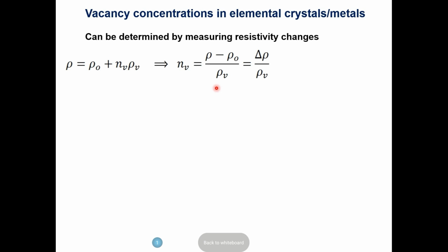Keep doing it—now go to 800 degrees, then 900, and measure the electrical resistivity each time. From the change of the electrical resistivity at different temperatures, you can figure out the amount of vacancies you are creating in the silver or aluminum.